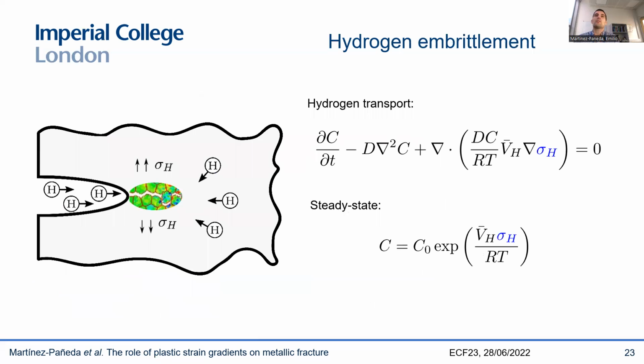And another area where this is very important is hydrogen embrittlement. We know that in the presence of hydrogen, or when we expose metals to hydrogen-containing environments, we have an uptake of hydrogen, and this reduces by orders of magnitude the fracture resistance, the ductility, and the fatigue crack growth resistance of metals. So it's very important here, and it's important for a number of reasons. The first one is that the amount of hydrogen that you have in your material depends on your hydrostatic stress. You can see it here. Hydrogen accumulates in areas of high hydrostatic stress.